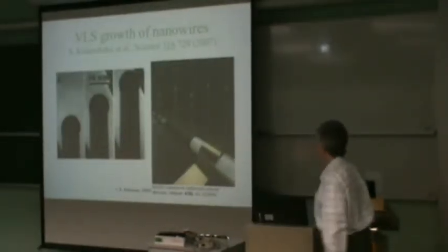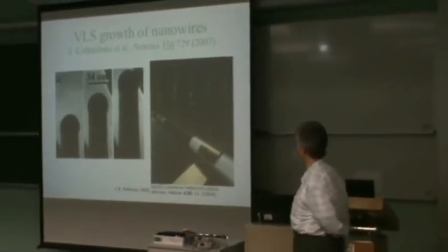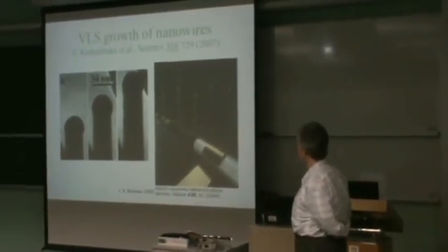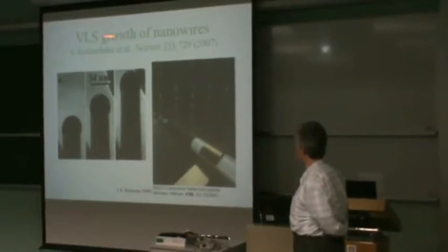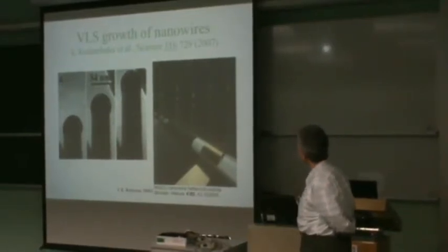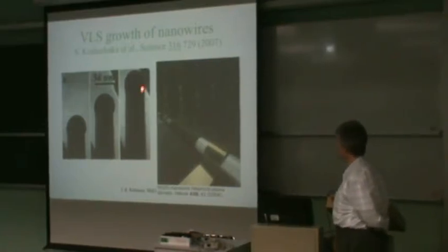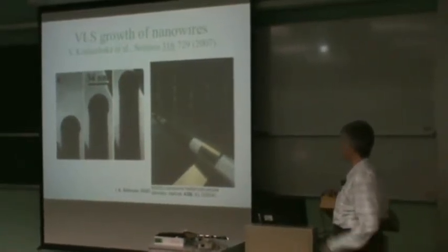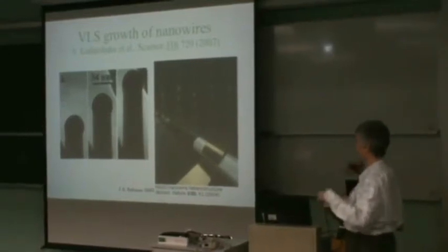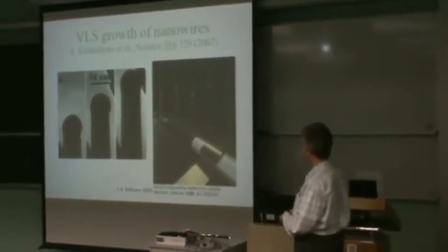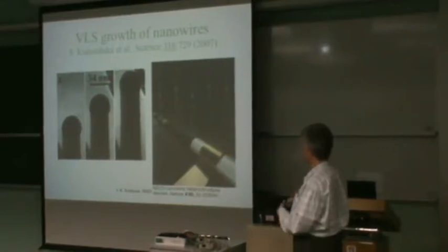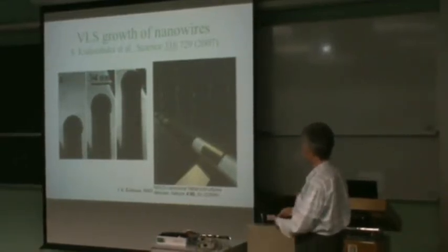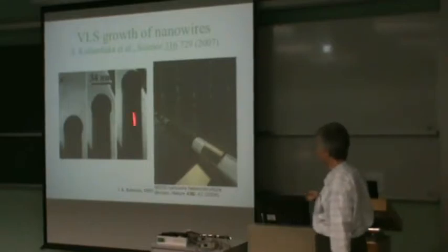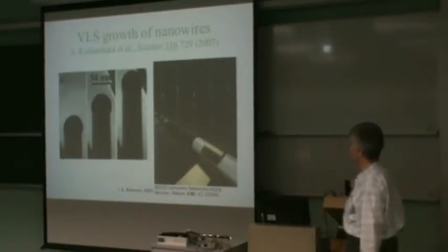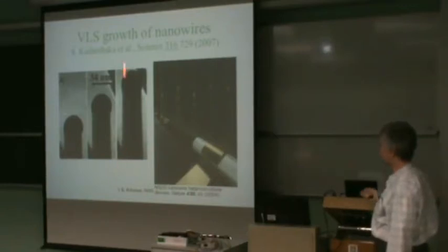Okay. So for nanowires, we've got a very nice method of growing wires called the vapor liquid solid method, which is where you use a catalyst drop and you do CVD, chemical vapor deposition of the material that you're trying to grow, and it dissolves in the catalyst, and when it becomes supersaturated, it forms a single crystal, and the single crystal is limited in size to the size of the drop that you've created. And so you can get linear growth of wire-like structures.